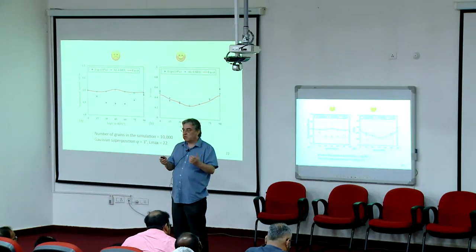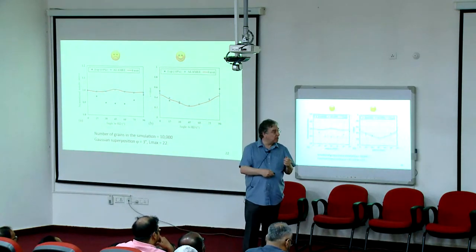So this means that if you know this set of n crystallographic grains, this distribution function of crystallographic orientation, as a microstructural state variable, this is the analog of the grain size in the Hall-Petch relation, then from that point on, if you have a good crystal plasticity model, we can predict the earing behavior. So that's a powerful structure-property relation.